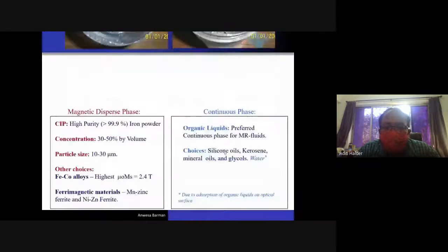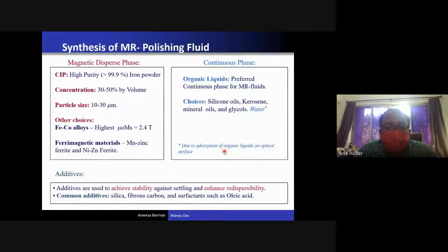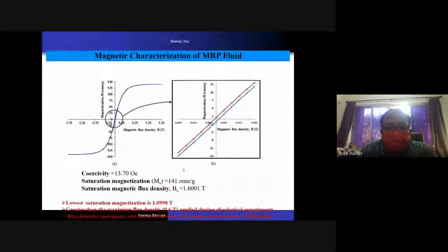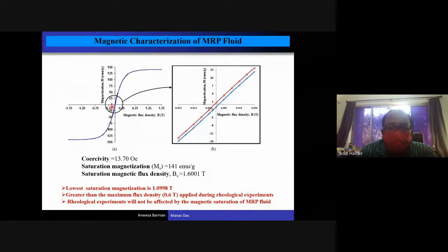Now, other than these carbonyl iron particles, other options for ferromagnetic particles are manganese zinc ferrite and nickel zinc ferrite. So these are the other options. This CIP has a unique property. It is 99.99% pure, and mostly 30 to 50% by volume is used inside MR polishing media, with a size in the range of 10 to 30 micron. And then you can see here, hysteresis is low.